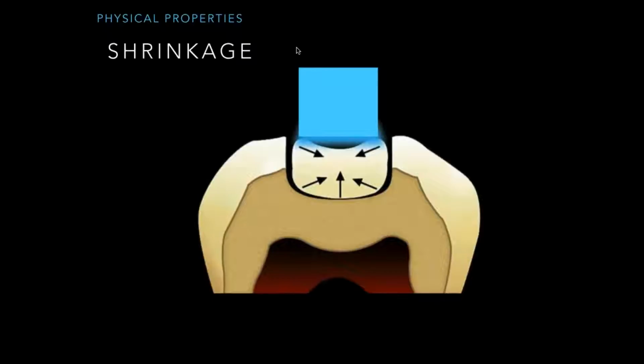From their chemical compositions, dental composites volumetrically shrink. Some shrink as little as 1.5%, others up to 5%. Shrinkage is the process of volumetric contraction that occurs when the composite cures. Materials that possess high shrinkage values can create voids, marginal discoloration, secondary caries, and allow for postoperative sensitivity. Obviously, you want to make sure that you select materials that contract or volumetrically shrink as little as possible.